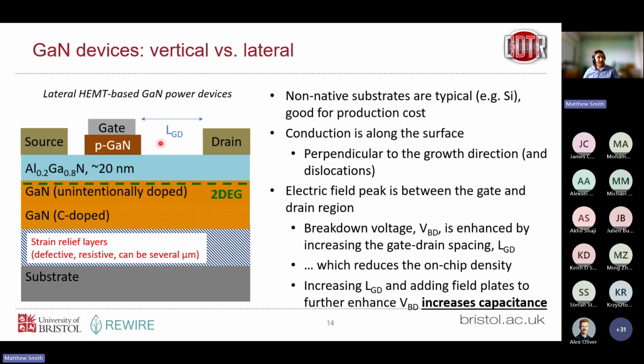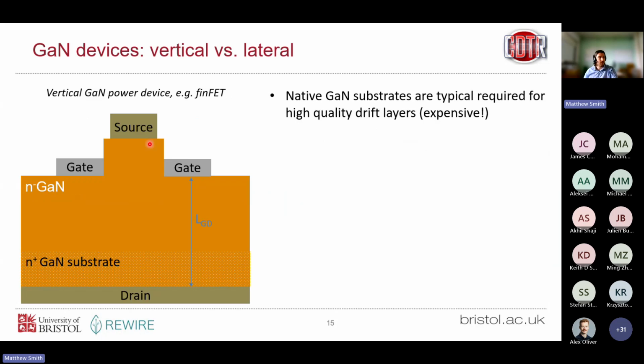And actually, this also increases capacitance. Usually when we make two electrodes further apart, capacitance goes down. But due to all the field plates and coupling between the 2-DEG and the gate in these devices, capacitance actually increases as we go towards 1 kilovolt.